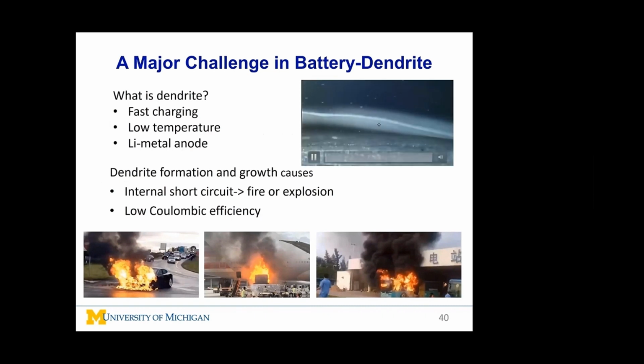This video shows the dendrite growth. You can observe the dendrite grows and pushes the separator. When the dendrite penetrates the separator and bridges the anode and cathode, an internal short circuit happens. This can lead to fire or even explosion. Dendrite also leads to low Coulombic efficiency.